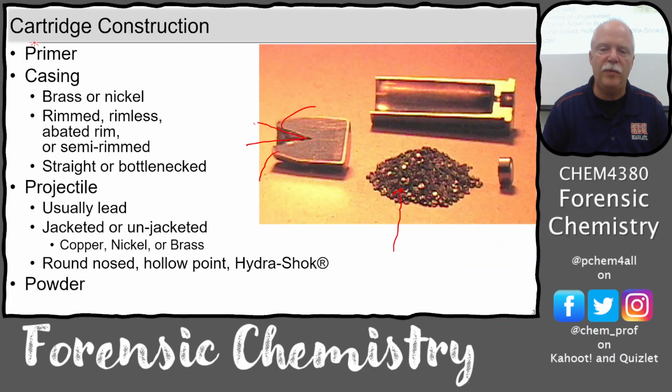I mean, we call it gunpowder, but it's not your grandpa's gunpowder. This is well-engineered, polymer-bound gunpowder. It's really small prills. It's not just some random powder dumped into a little case. They're little pressed pellets, kind of through a micro sausage grinder. Like they make this slurry and they squeeze it through, and all the little prills break off. So they have a pretty well characterized surface area, so that they burn at a certain rate. You want them to burn mostly inside the rifle or the pistol, so it generates the most pressure to get that bullet out as fast as possible.